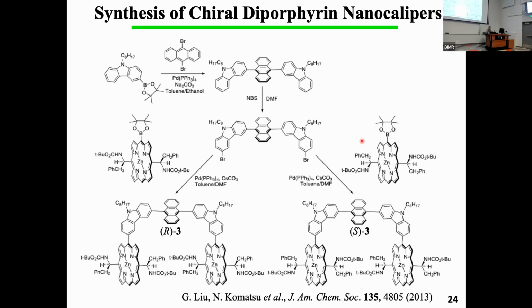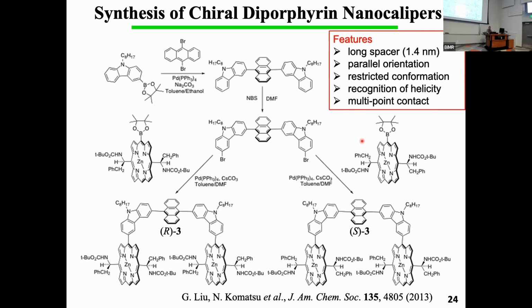And this is the nanocaliper synthesis procedure. Of course, we finally use Suzuki coupling reactions to connect the two porphyrin units to this kind of spacer. The characteristics of the nanocaliper are a very long spacer, 1.4 nanometers, the parallel orientation of the two porphyrin units, and a restricted conformation, especially since there is a single bond between the porphyrin and this spacer. This is somewhat restricted. And there is recognition of the helicity by the stereogenic center at the periphery of the porphyrin unit.